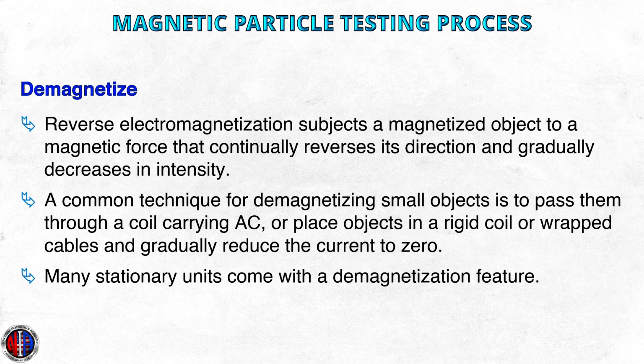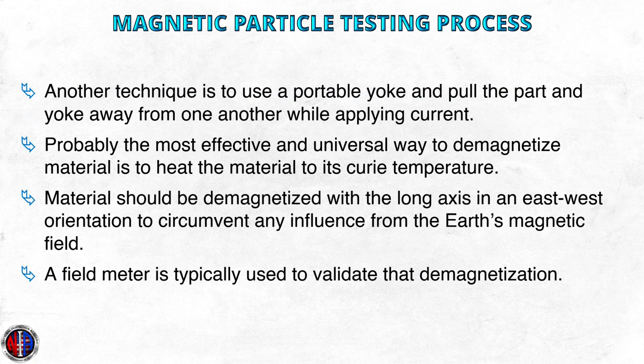Many stationary MT units come with a demagnetization feature that slowly reduces the AC in a coil in which the component is placed. Another technique is to use a portable yoke and pull the part and yoke away from one another while applying current. Probably the most effective and universal way to demagnetize material is to heat the material to what's called the Curie temperature. When material is heated above its Curie temperature, it loses its magnetic properties.